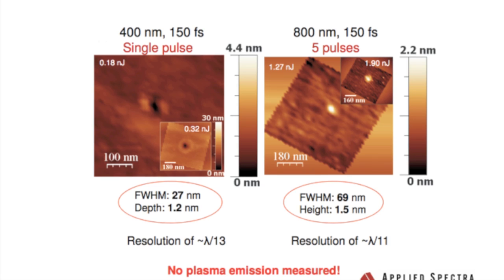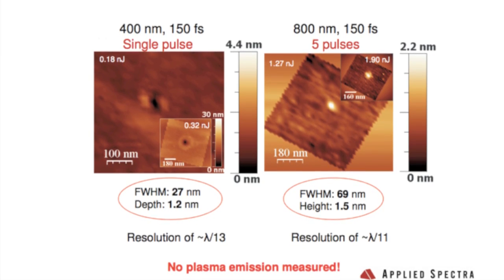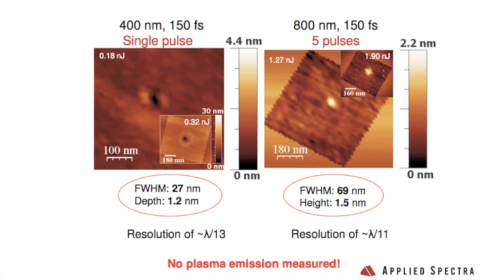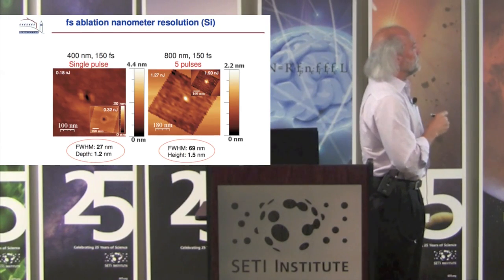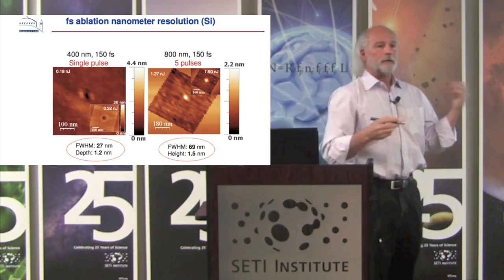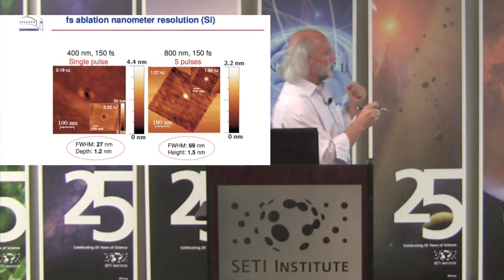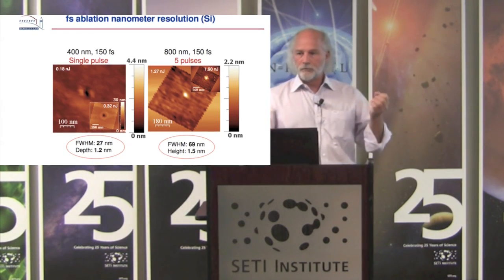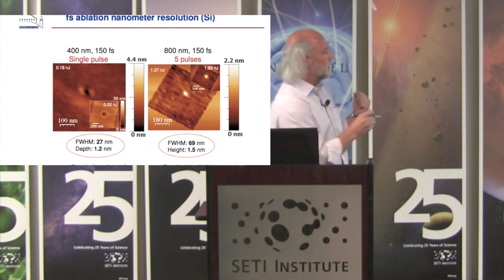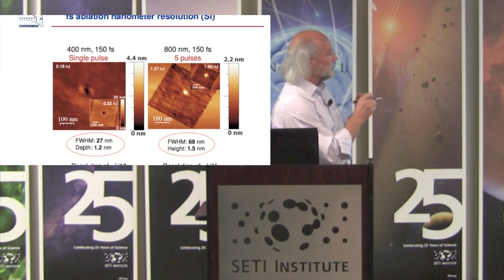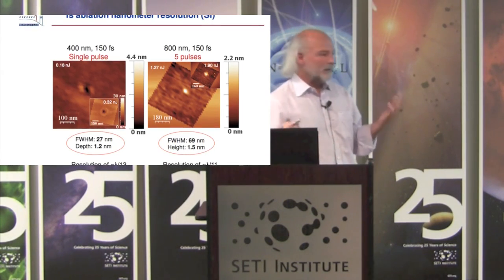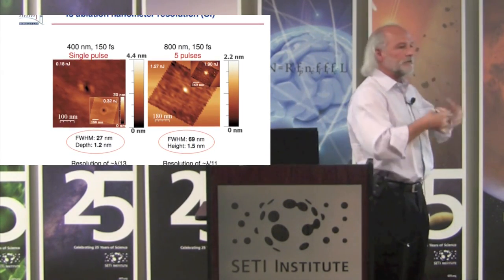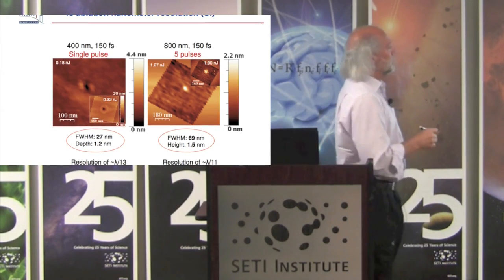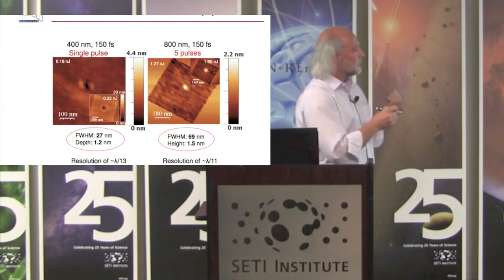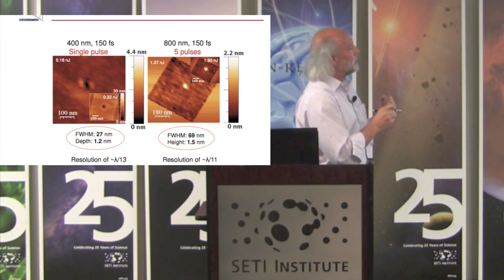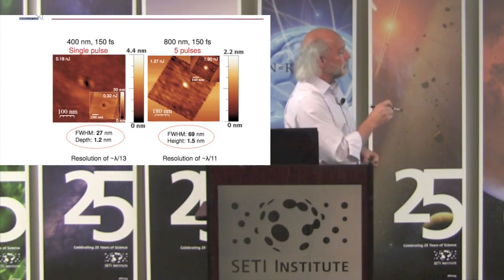And again, there's some wavelength dependence. So if we use 800 nanometers from our femtosecond laser, the crater size is a little bit bigger. So we can do laser ablation down at this level. However, we have not measured any traditional LIBS plasma, okay? At this point, we've got about 10 to the 8th, 10 to the 7th, 10 to the 9th, depending on what the density is. That's as many atoms as we've ablated. I don't even know if there are collisions that are causing light, okay? And if there is light, I'm not getting it out of the near field.